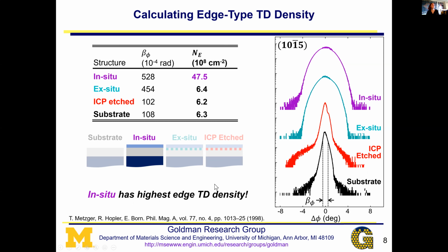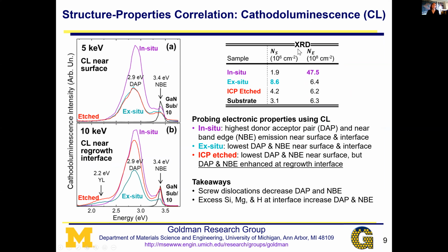And so now the interesting part is to connect this structural analysis that I did with XRD to the electronic properties that were investigated using cathodoluminescence, which probes the luminescence of the sample at both regions near the surface, which is this top plot, as well as regions near that regrowth interface of interest, which is the bottom plot. These two plots are virtually identical, except for one key difference, which is that for the ICP etch sample, the donor acceptor pair emission peak increases from the surface to the interface. And so you see this recovery of some of the electronic properties of this sample.